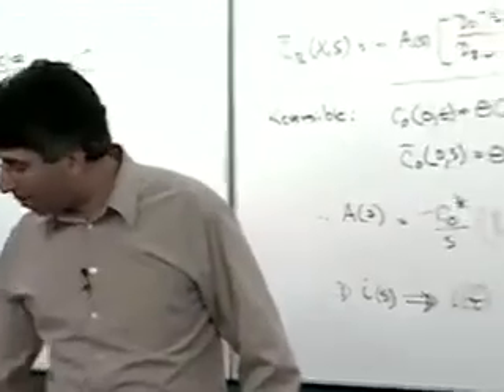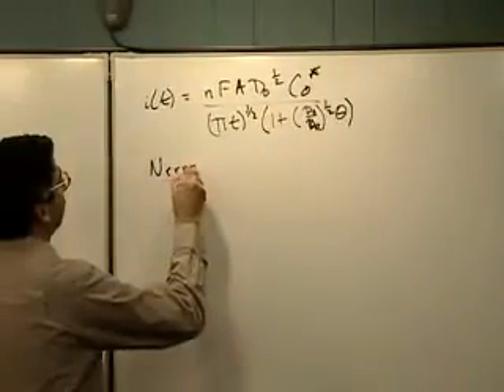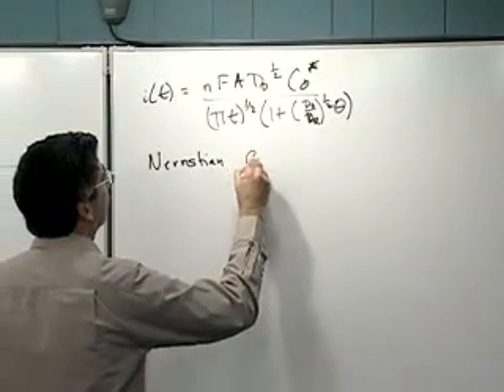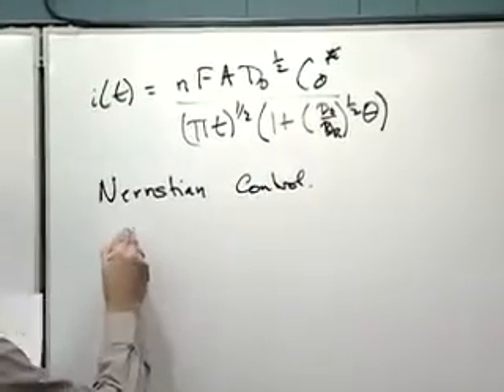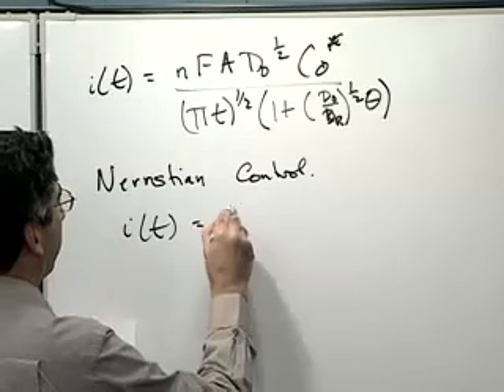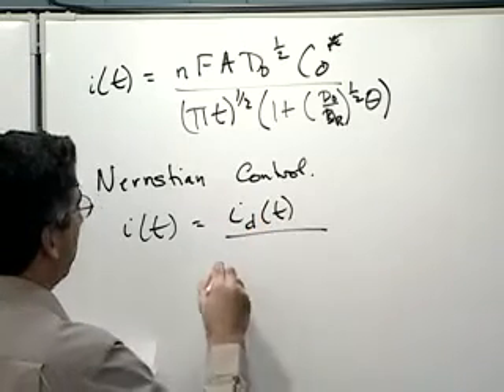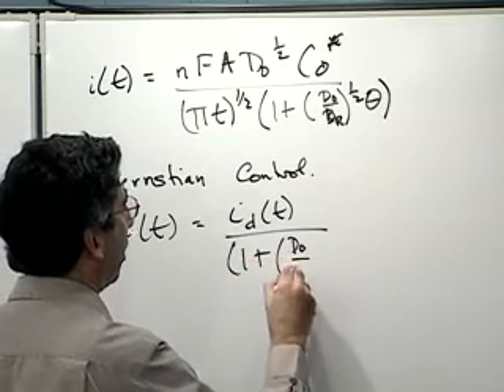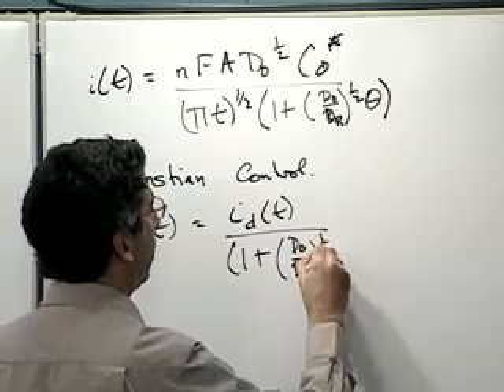So my statement that I made a moment ago, that when we do a potential step that's smaller than the diffusion limited potential step that is controlled by the Nernst equation, we'll get a curve that looks just like this curve. It has the same functional form, but the current will be smaller for all times, with the exception of time equals 0, where it goes off to infinity. Okay. So if you wish, I could then just rewrite this current as equal to the Cottrell current, i sub d, divided by this 1 plus the ratio of oxidized to reduced to the 1/2 times theta term.